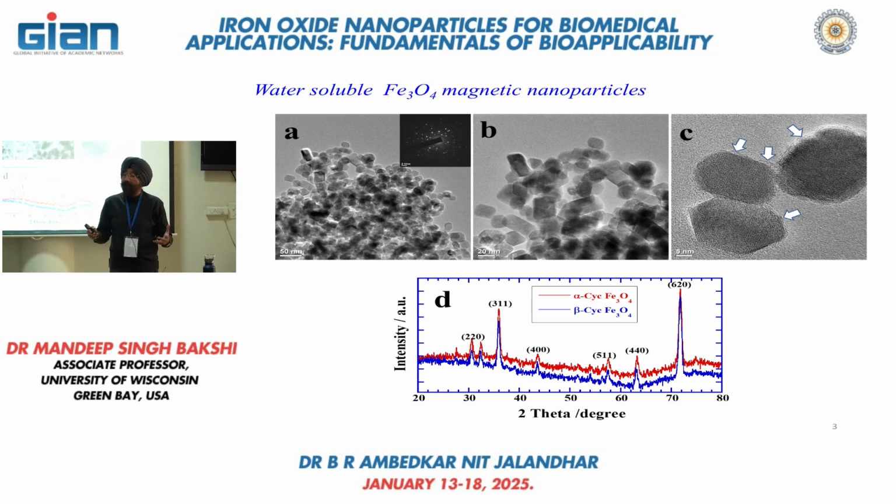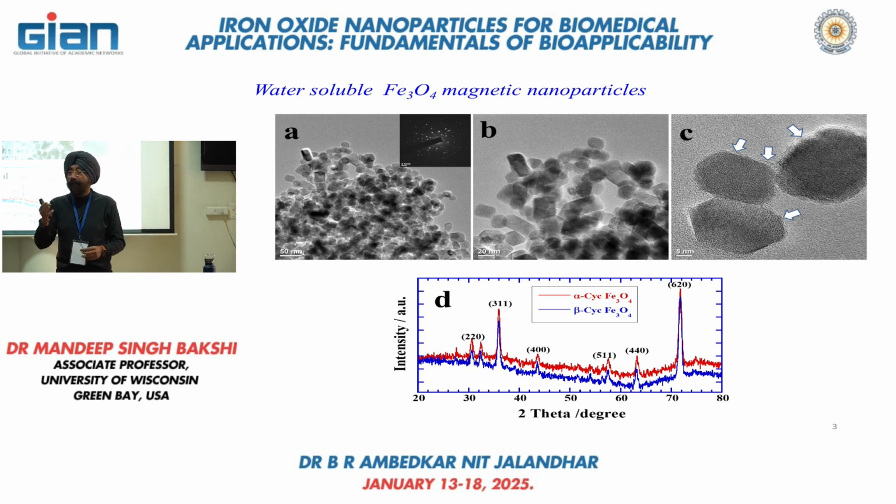You have learned that in the lab experiment, you used 250 mg of a Gemini surfactant to synthesize the surface active magnetic nanoparticle, because we have standardized the conditions accordingly to get the smallest possible size.